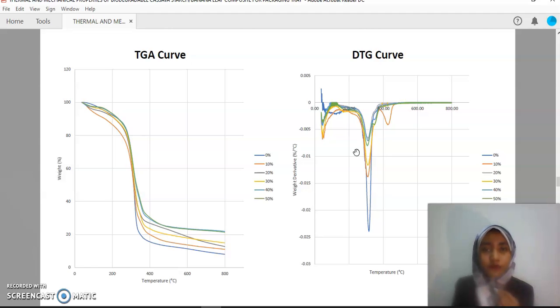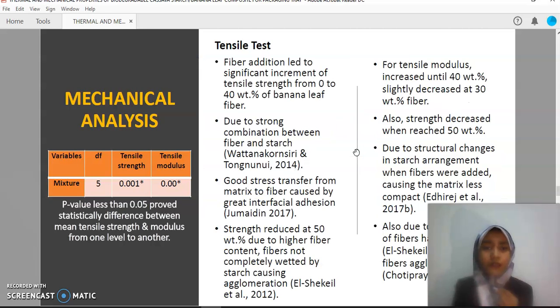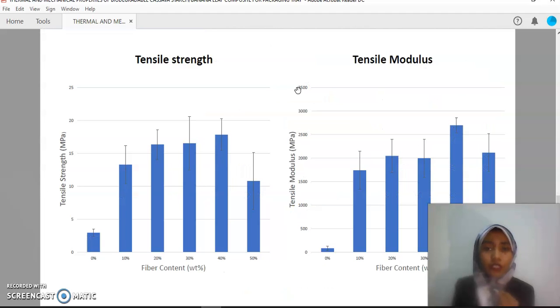Okay, so we know that the thermal stability increases when the fiber increases. And then for mechanical analysis, the tensile test, here is the result. We can see that the optimum fiber content is at 40%. The fiber addition led to a significant increment.